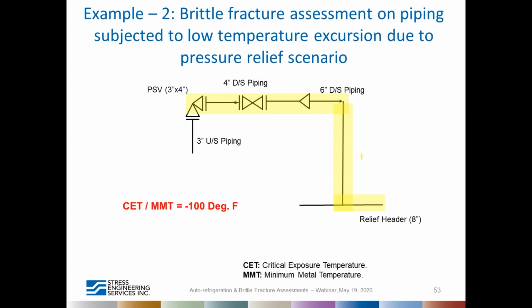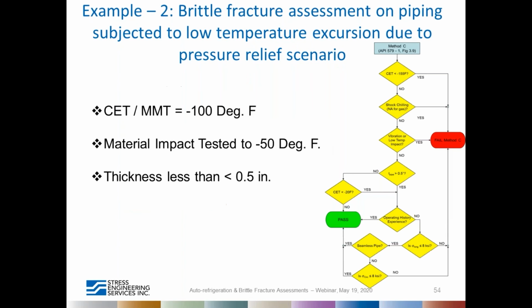Regardless, flaring is a common phenomenon, and relieving is a common phenomenon happening both in topsides and downstream and other operating facilities. So how do you address such a relieving scenario or a flaring scenario? There's a PSV here. This is an example problem involving a piping system, and then there's a downstream pipe. In this case, the CET was established to be -100 degrees Fahrenheit, and you run it through the Level 2 assessment procedure. The easy assessment would be Method C, which involves the flow chart.